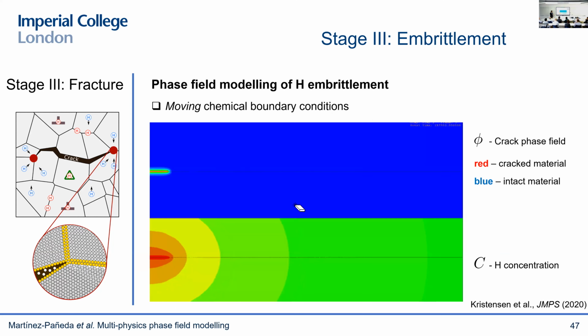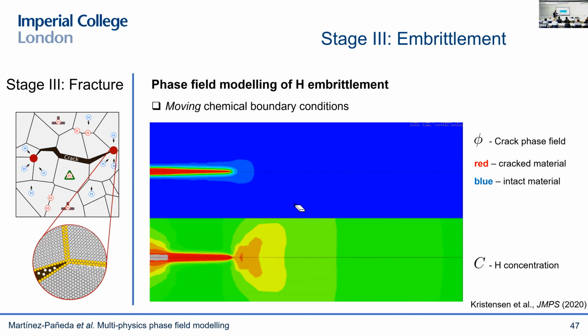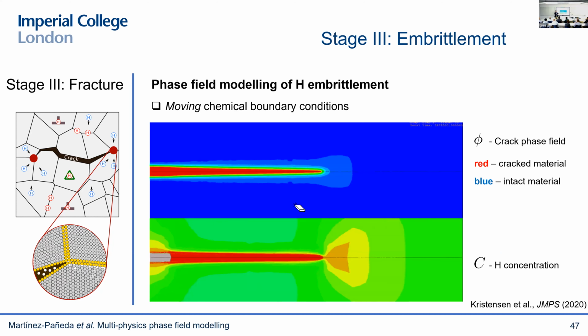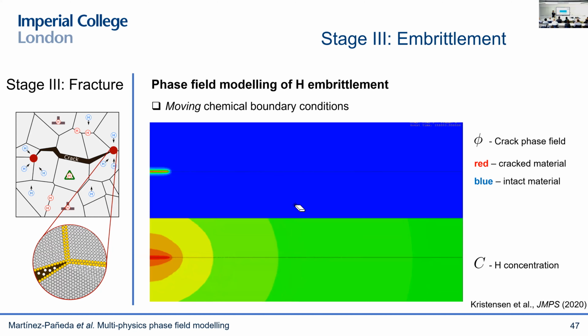So let me show you some representative results with this framework. One thing that I would like to say as well is that this is a critical crack growth problem, so we're not only interested in initiation of cracks, but also in the propagation, and therefore we need to be able to capture how, as the crack propagates, the hydrogen-containing environment follows. So imagine a pipeline in the middle of the sea. As the crack propagates, the seawater will immediately become in contact with the newly created crack faces. And we do this through a penalty approach, but of course there's multiple ways of doing this.